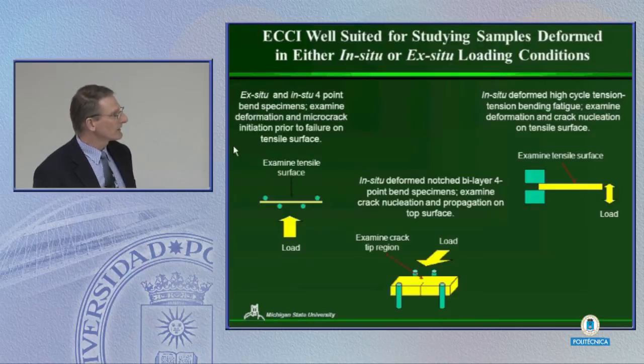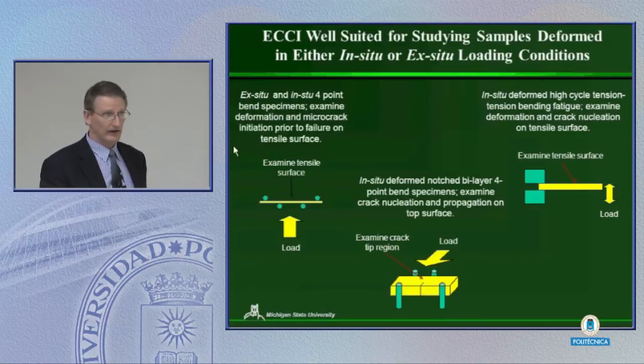We can also look at the sides of 4-point bend specimens in situ, and I'll show you some examples of this. This is quite useful for us to get a general feel for how a crack is propagating. And finally, we can actually do some fairly high cycle fatigue in bending too, which again allows us to look, for example, at the tensile surface in a fatigue sample. We have a stage that will go at about 500 cycles per minute on our microscope.